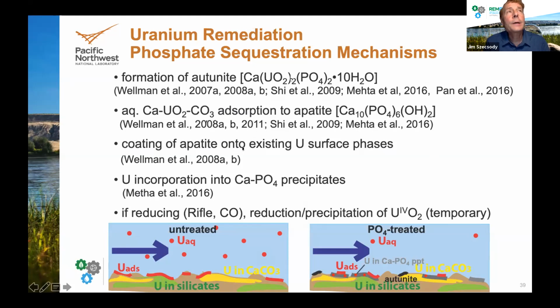The apatite can also coat existing uranium surface phases, and uranium can actually incorporate into some calcium phosphate precipitates. And these 4 mechanisms are likely occurring in some combination at Hanford Site. Now I'll touch on the Rifle site, and there's an additional mechanism that can happen because the system became a little bit reducing, so we can actually form some uranium-4 and that'll precipitate out.